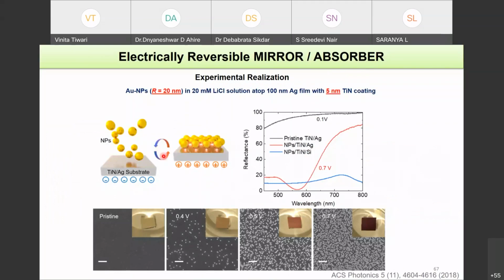So when we did experiments, it was very similar setups. You have silver substrate, but now to protect the silver from oxidization, 5 nanometer titanium nitride film was deposited. So this is just a protective layer, and these are the gold nanoparticles in the 2 different phases. And you see, when low potential is applied to the electrodes, okay, so nanoparticles are not attracted towards the silver substrate. So you get a silver substrate giving you a very good reflectivity, almost 90, 95, 96%. Or here it is something around say 92% or so.